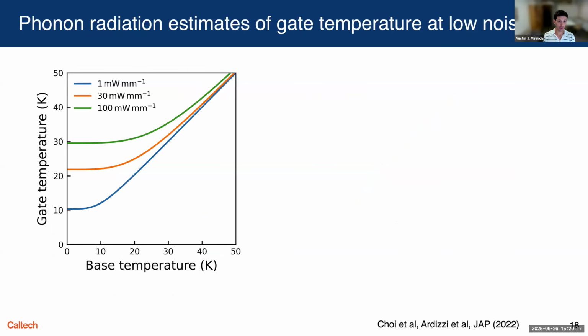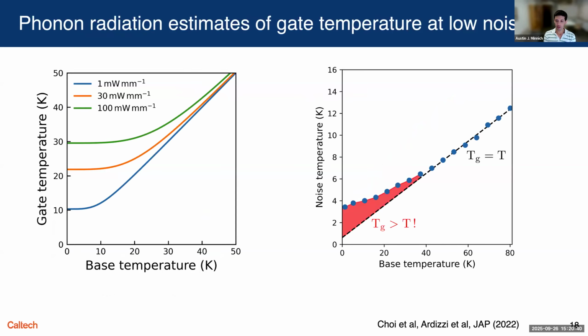Okay, so with that key insight, we can make another little model which predicts the gate temperature versus base temperature for different power inputs. And that result is shown on the left. And what it says is that for any practical power input, there's a plateau in the gate temperature and therefore in the gate noise as well. And so this is some pretty firm evidence that the limits of noise performance in part for these HEMTs is really driven by self-heating, and that leads to this noise temperature plateau.